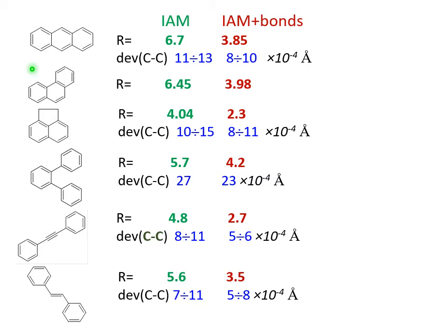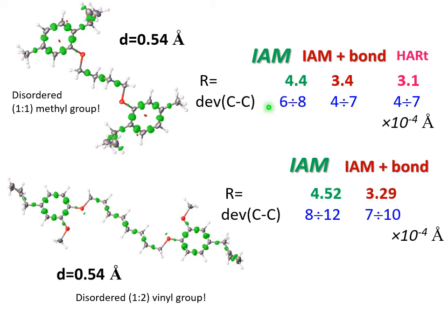This stays with us for any aromatic compound. We have around 40 to 50% improvement when we apply scattering center to our aromatic compounds. If you are coming to the compound we started with, it's not only aromatic but also aliphatic residues where this effect is less prominent, but still have nice improvement of our data. Of course, Hirshfeld atom refinement is even better, but not by much.